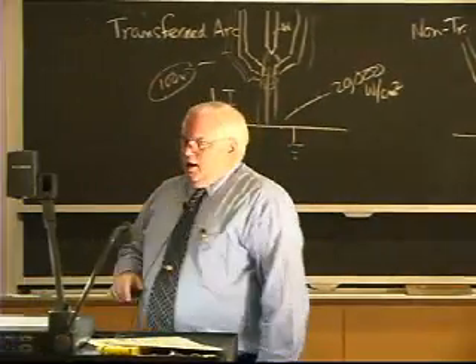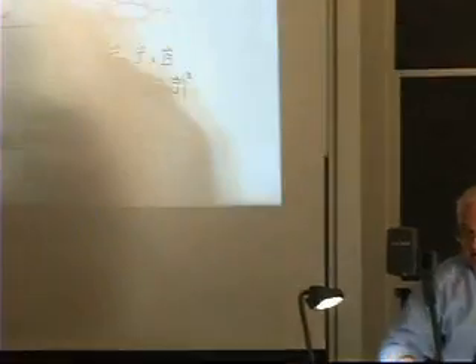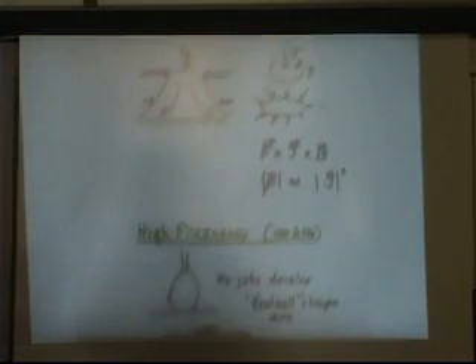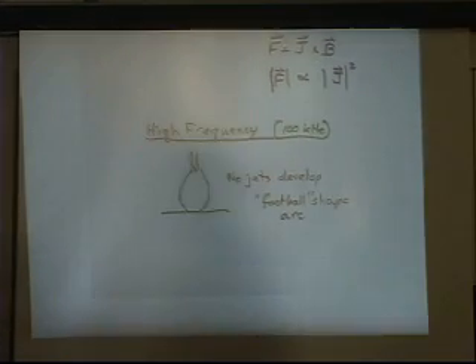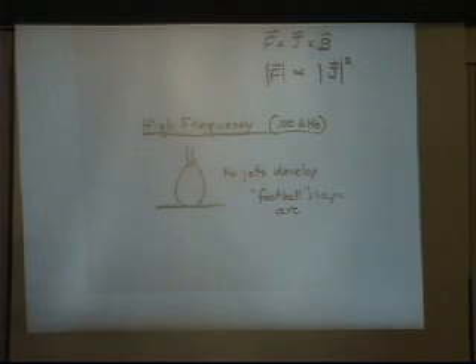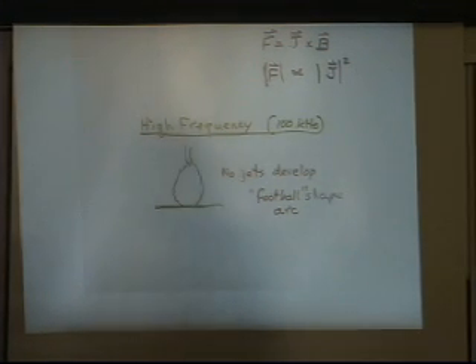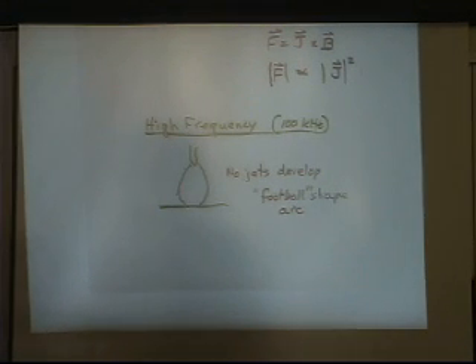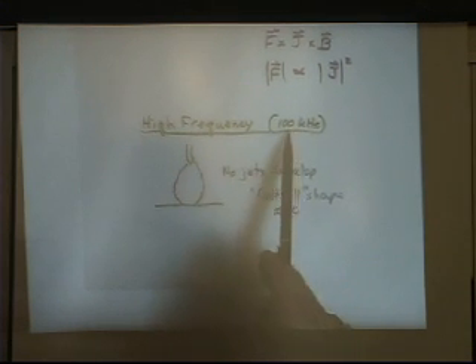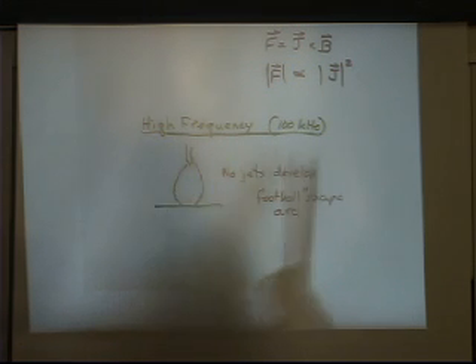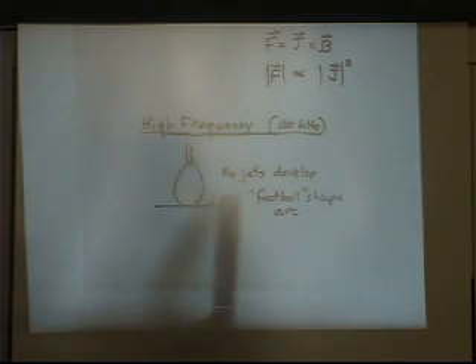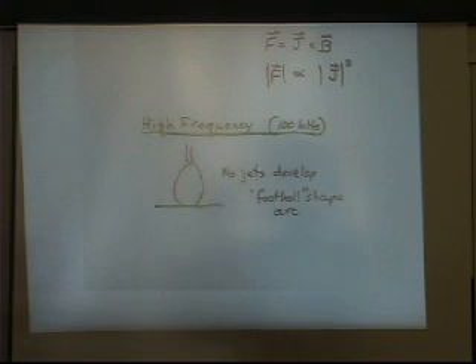Okay? And this jet coming down creates this flow, which creates the boundary layer. It turns out if I go to very high frequency arcs, and I actually can get some arcs, well, with special power supplies, up in this 100 kilohertz regime. You asked me the other day about the response time of how quick the arc could go on and off. The plasma frequency response time is on the order of 100 kilohertz. If I actually turn the arc on and off at 100 kilohertz frequency, I will not develop the plasma jet, supposedly, and I get a football-shaped arc as opposed to a bell-shaped arc.